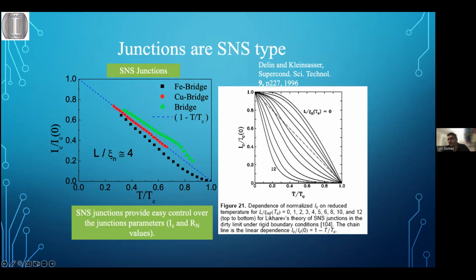So I plot the data. I chose to plot the data in this fashion to compare it to classical results published in the review paper by Delin and Kleinsasser, for high temperature superconducting Josephson junctions. You can see that the bridge that has the iron behaves like another Josephson junction made with high temperature superconductors, and it has this curve shape, and the others do not. So that's another indication that maybe what we made can be comparable to other types of high temperature Josephson junction systems.